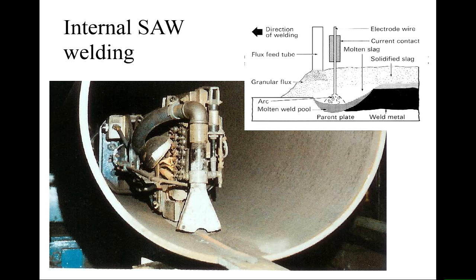And when the metal solidifies, they'll end up as this slag layer sitting on the surface. So the flux is chosen so that you have elements in there that can react to make these slags easier to form. So a protective flux might contain some carbonates, and when you heat carbonates up, they give off CO2, and that CO2 might be the protective gas. And then the calcium oxide can react with iron oxide to form a low melting point oxide that will float on the top and protect the weld pool.